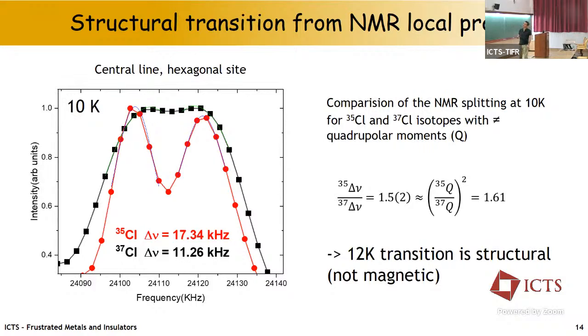Maybe I will skip that. We make use of the fact that there are two chlorine isotopes, actually, with two different quadrupolar moments. So by looking at the splitting of the line for the two isotopes, you can decide whether the reason for this splitting is quadrupolar in origin, structural, or magnetic. And it turns out that it fits well with a structural transition, which was expected already from thermal expansion and heat capacity.